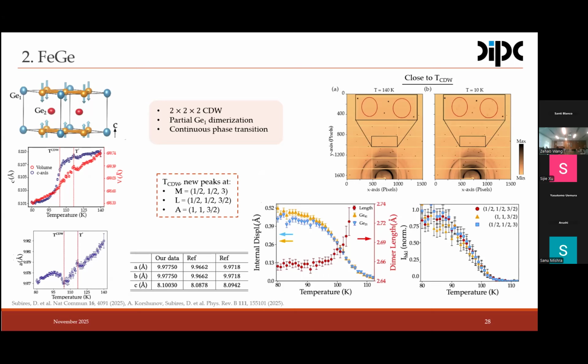Right, so we know that many people are working now on the annealing conditions just to play around with these charge orders. Some people get more first order, some people more second order. The as-grown crystals we got from Dresden show a continuous, second order like phase transition. And we can actually track the temperature dependence of the lattice parameters. You see how they face the charge order at 98 Kelvin, 95 Kelvin, and some kink in the A around 115, 120 Kelvin. So we'll come later to this T star temperature when analyzing the diffuse scattering.